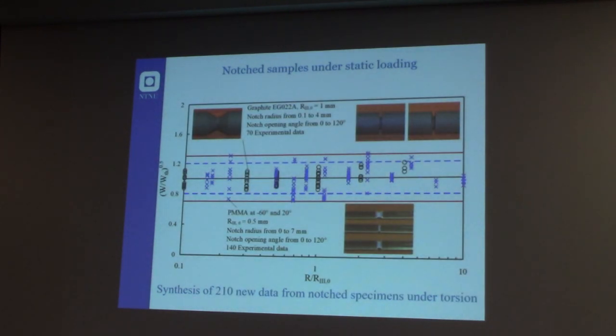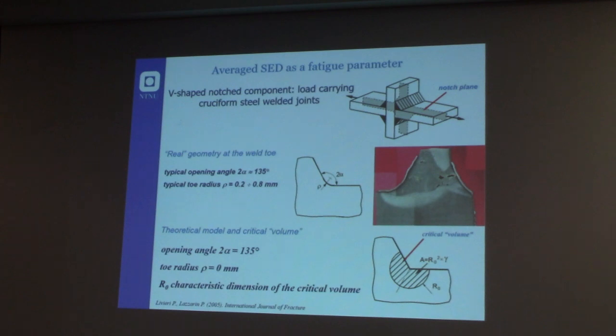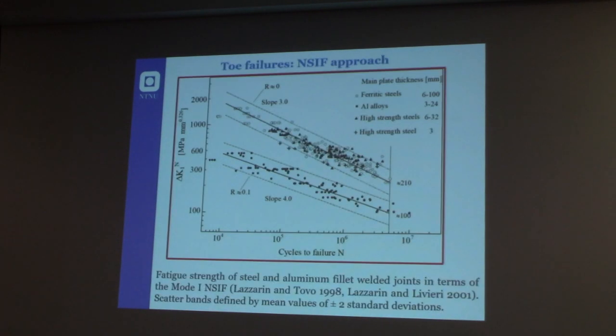And we also applied this to graphite under mode 1 and mode 3 loading. Actually, this was the first time that we applied the strain energy density criterion to mode 3 loading. And of course, we also applied the same consideration, first, to the data that Lazzarin and Tovo obtained in 1998.